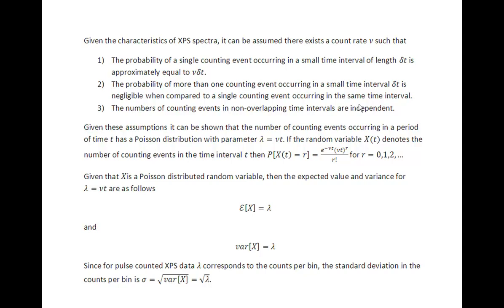What we are assuming is that it doesn't matter when we measure these counts. Whatever time interval we choose, they are quite independent of time, and therefore we can quantify carbon against oxygen or silicon — they all occur as independent events in separate time intervals. So this third condition is also what we expect for XPS data.